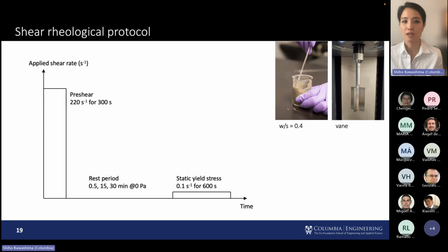So this is our rheological protocol. We did focus on the cement paste phase. So we can use a stress controlled rotational rheometer, fix the water solid ratio, use a vane geometry. And so this is our protocol here. We apply a pre-shear, and that is so that we get to some reference state across all samples, across all tests. And we were interested in the evolution of various properties, including the static yield stress and the dynamic yield stress. So we imposed different rest periods from 0.5 minutes to 30 minutes. And then we applied an intermediate shear rate, so a relatively slow shear rate over 600 seconds.